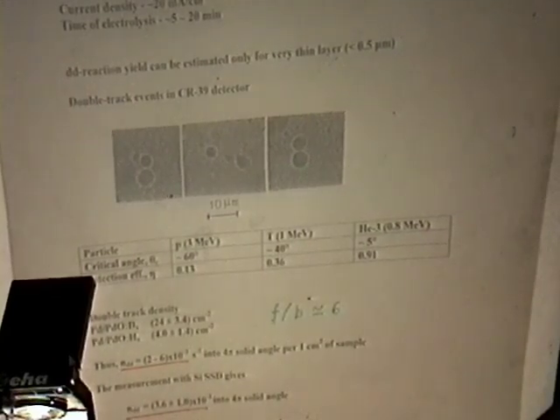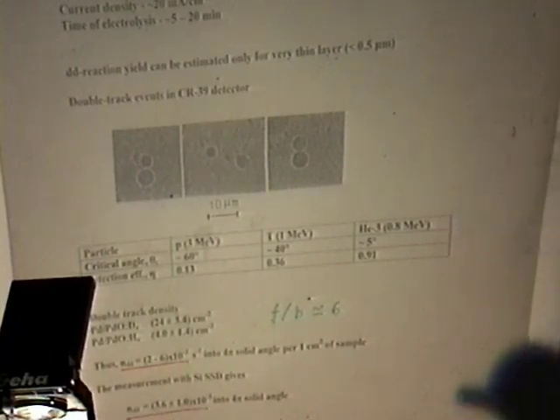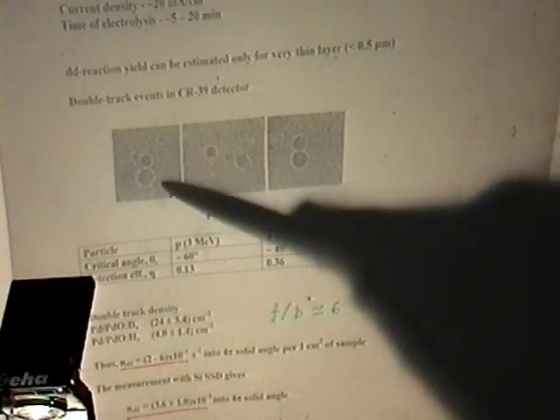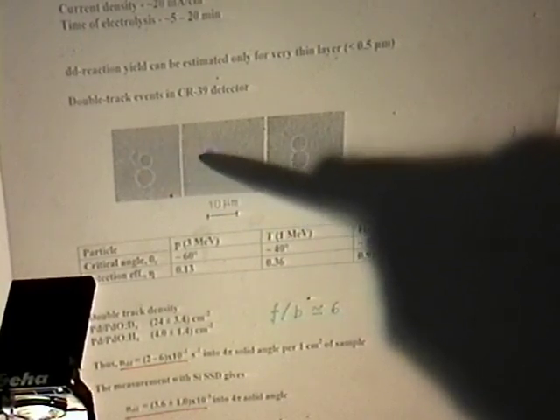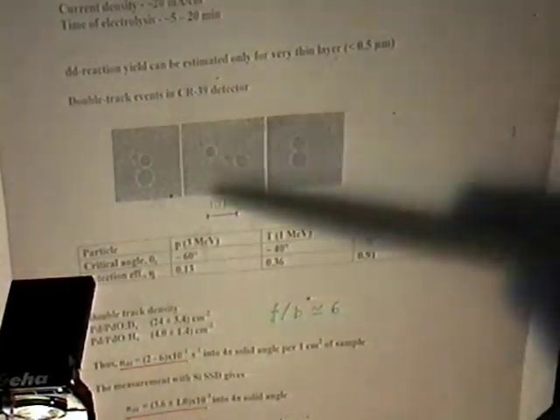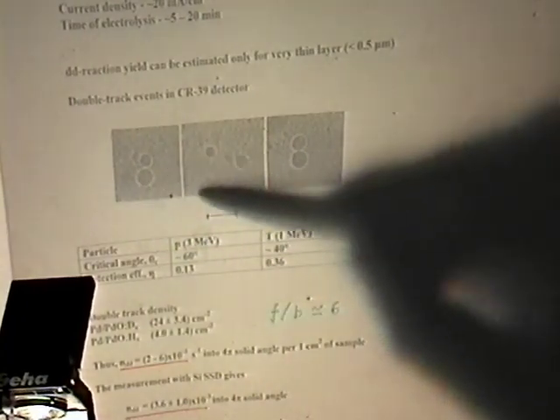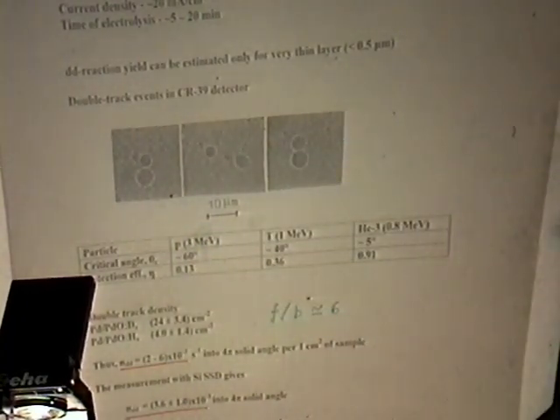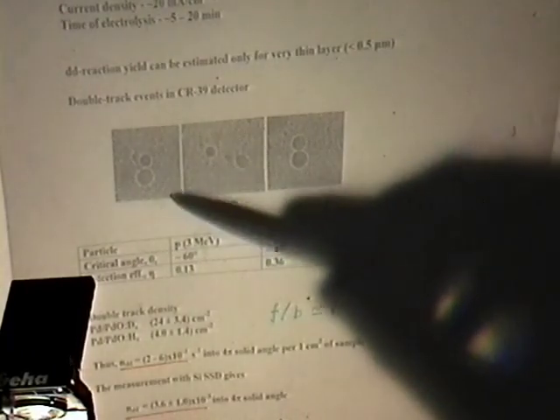To estimate the reaction yields, we use the same procedure. According to calibration measurement, we try to count the double tracks, when the track with diameter near 5 micron is near a second track with diameter between 6 and 7.5 micron. The first track is attributed as a proton track, and the second as a tritium or helium-3 track.